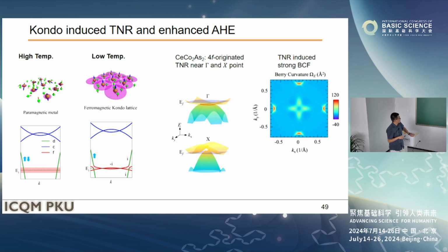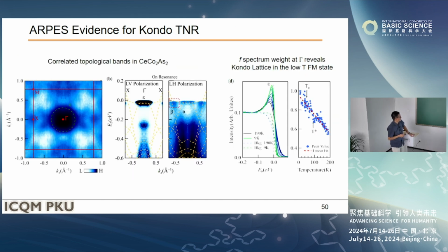The picture is that at high temperature, the f electrons and the conduction electrons are decoupled. But at low temperature, it forms a Kondo lattice, meaning in k space, it forms a very narrow band near the Fermi surface. For this compound, it forms a narrow topological nodal ring, and this topological nodal ring has a significantly strong Berry curvature field that gives you a large intrinsic anomalous Hall effect. So this is an ARPES measurement that gives you some evidence that they observe the topological nodal ring for this compound.